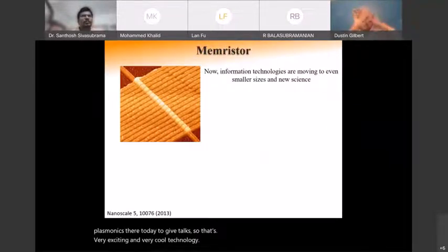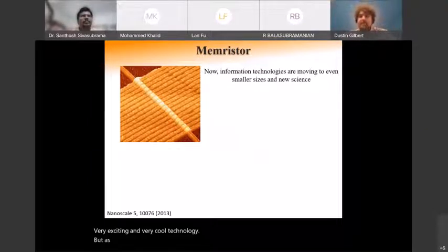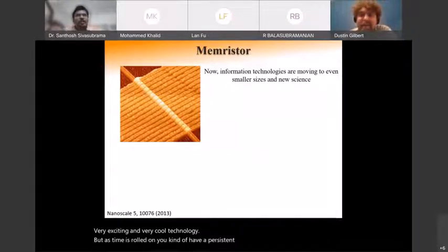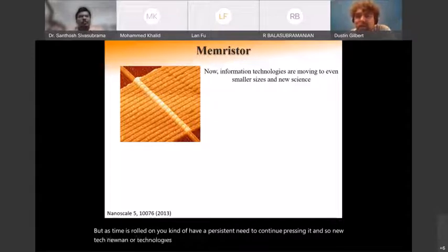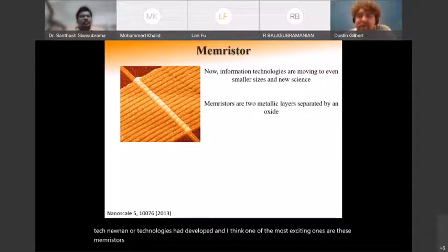But as time has rolled on, we have a persistent need to continue pressing it. And so new nanotechnologies have developed, and I think one of the most exciting ones are these so-called memristors. Memristors are 2 metallic layers spaced by an oxide layer. So in this picture, you have a metallic wire running from upper left to lower right. Then you deposit oxide crossbars and a metallic capping layer.